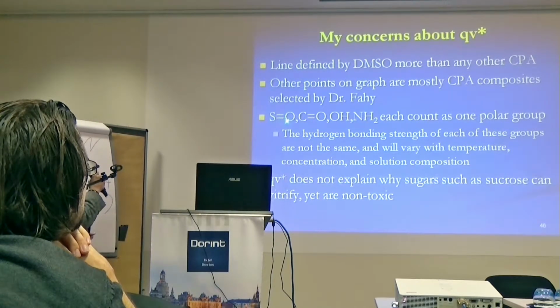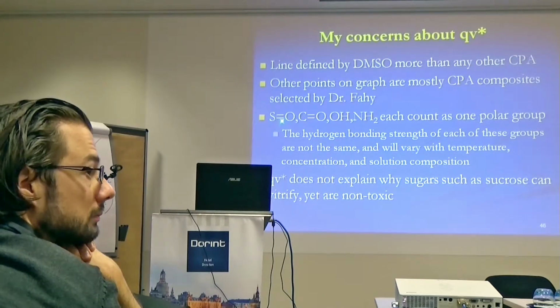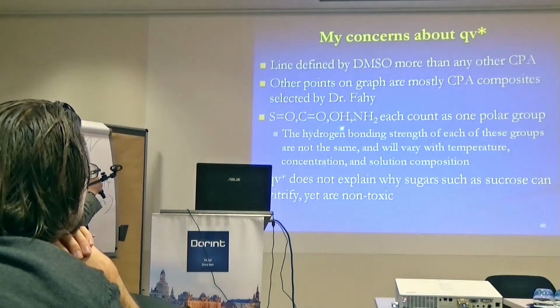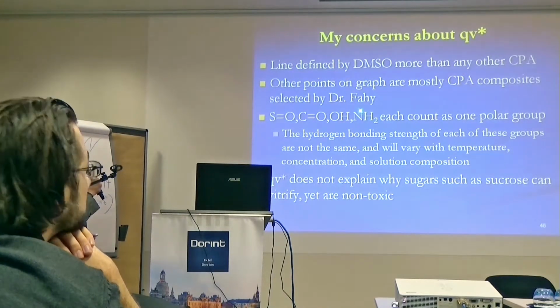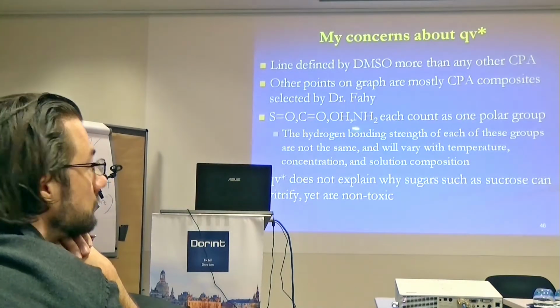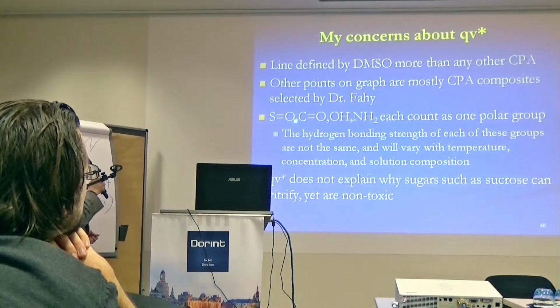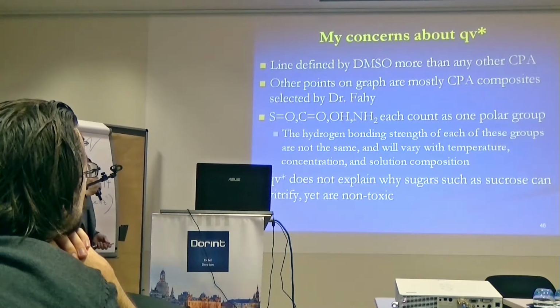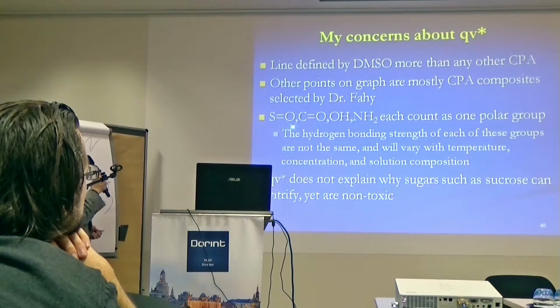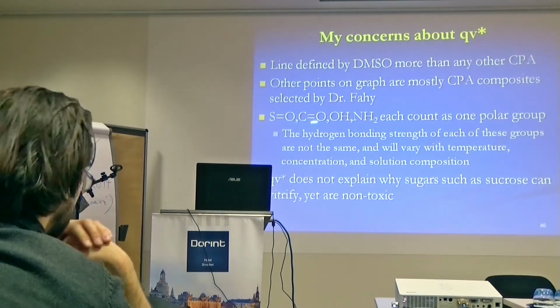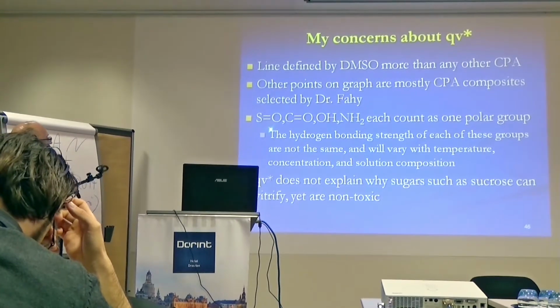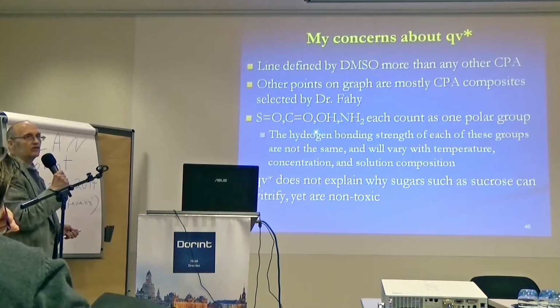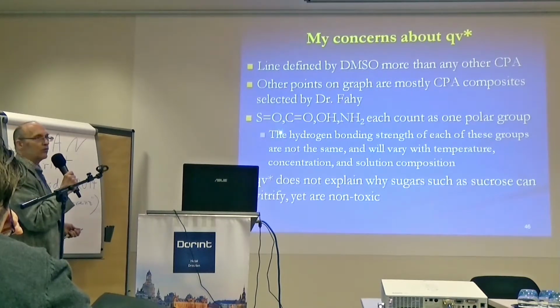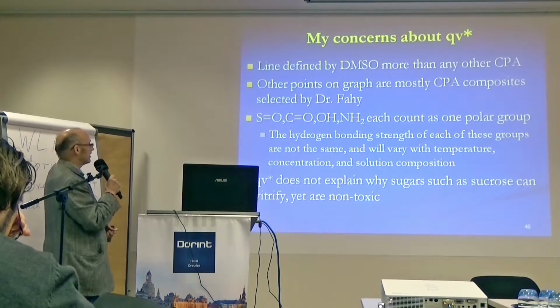This is what he counts as the polar groups: the sulfoxide group, the carbonyl group, the hydroxyl group, and the amide. They each count as one polar group, and they're all equated as being the same. And the hydrogen bonding strength of each of these groups is not the same; it varies with temperature, concentration, and solution composition. The best textbook I can find on hydrogen bonding, and I haven't given up looking for these sources, doesn't even give exact numbers for the hydrogen bonding strength of each of these groups, and it just gives a range, and even a range for categories.